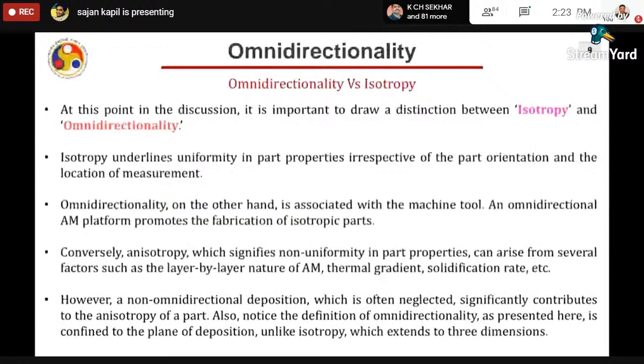The very famous reason is we build the part layer by layer. Usually, the strength of the part is less in the build direction, while in the other two directions it is higher, and that makes the part anisotropic, because of the nature of the process itself. But on the other hand, omnidirectionality is on the machine tool side. So non-omnidirectional deposition, which is often neglected, significantly contributes to anisotropy of the part itself.